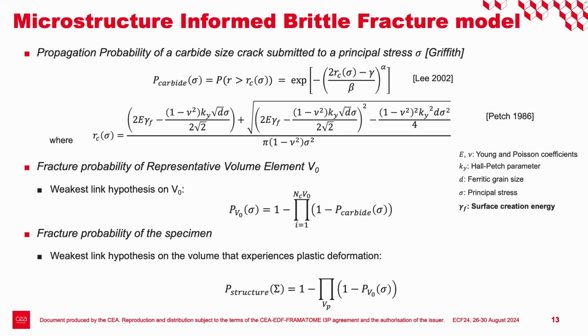So once we can compute the probability of propagation for the size of one carbide, we can compute the survival probability of the reference volume element. Using a weakest link hypothesis, the survival probability of your RVE is the product of the survival probabilities of all the carbides that are inside your RVE. And then at the macroscopic scale, we can compute again with the weakest link hypothesis: the survival probability of your structure is the product of the survival probabilities of all your RVEs that have been exposed to plastic deformation. That's why we use a product here.